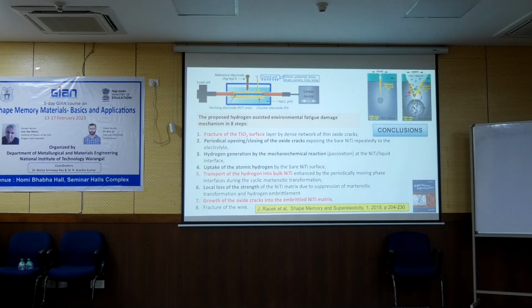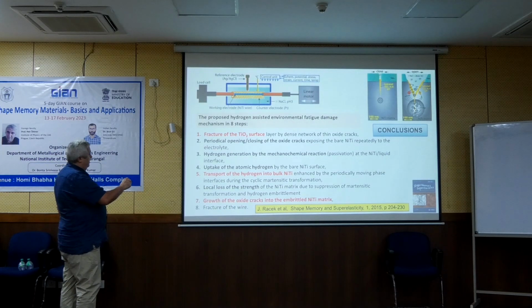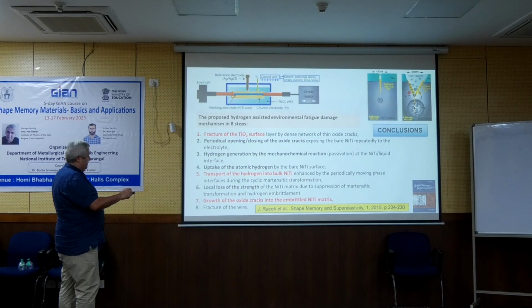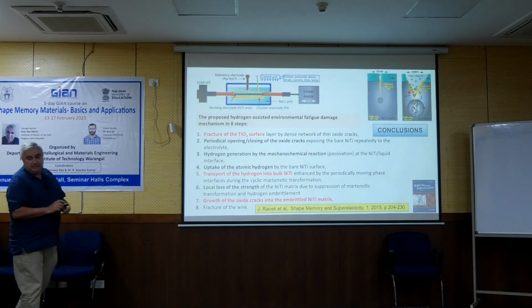So maybe I will not go into the detail. There is this article, and in the article there is a detailed description of this, we call it the hydrogen pump. There are important steps which I try to explain. The most important is fracture of the oxide, then creation of hydrogen by the opening and closing of the crack, transport into the bulk, and the hydrogen in the bulk supports the growth of the oxide cracks into the matrix.